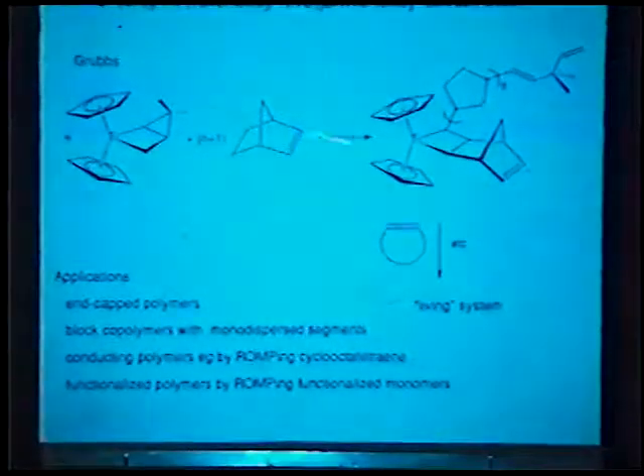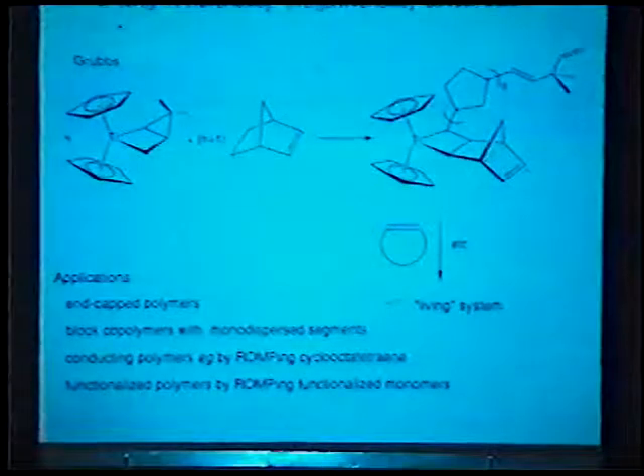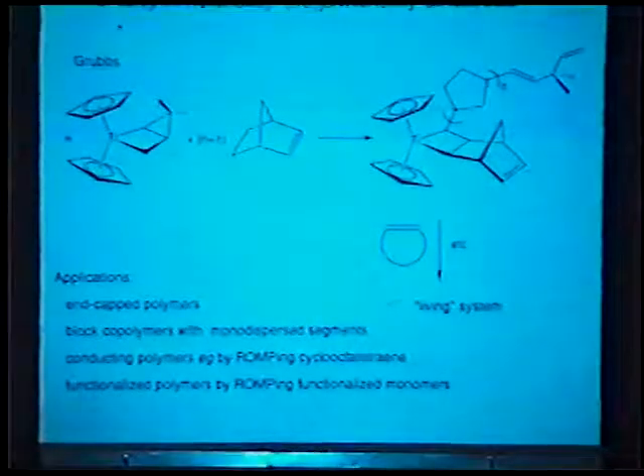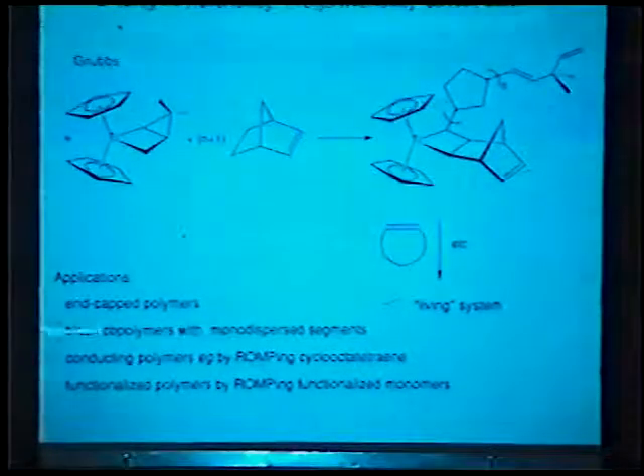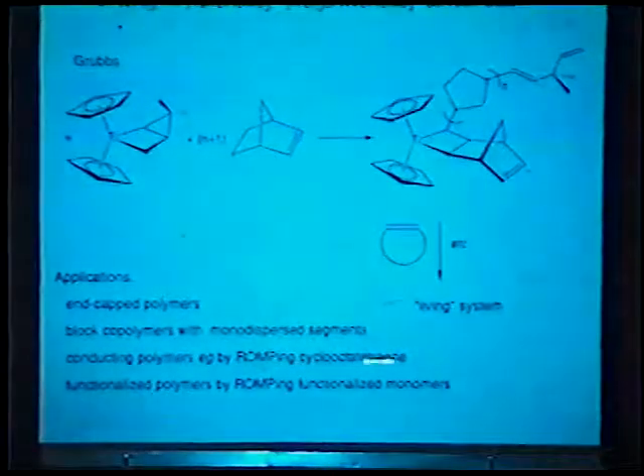But the point is, one gets monodispersed systems that are living, and in fact, you can add more monomer to get a higher molecular weight, or more interestingly, add a different cyclic olefin, and prepare not only end-capped polymers, but block copolymers with monodispersed segments. This group has also explored the synthesis of conducting polymers by ROMP of cyclooctatetraene, and impressively, with some new ruthenium-type catalysts, explored the preparation of functionalized polymers by ROMP of functionalized monomers.